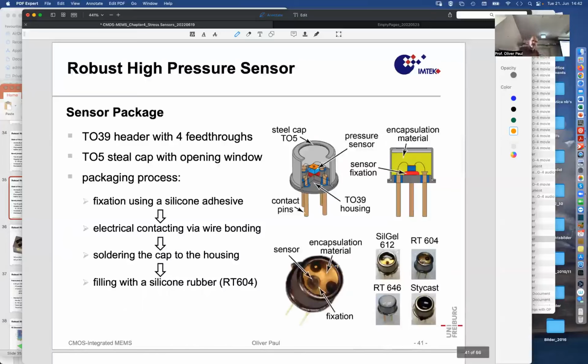And also how to package such a sensor. So here's a standard TO39 housing where the structure could be bonded to 4 contact pins, sitting on some flexible support. You do not want to bond the sensor onto the metal housing, because then you would prevent its contraction under the isotropic pressure. So elastically deformable material below, which is also a challenge, because elastically deformable materials under 2000 bars or even 600 bars deform a lot.